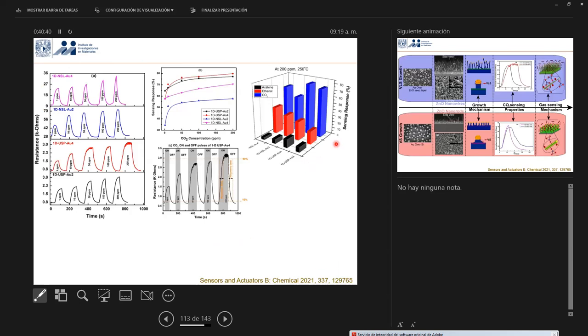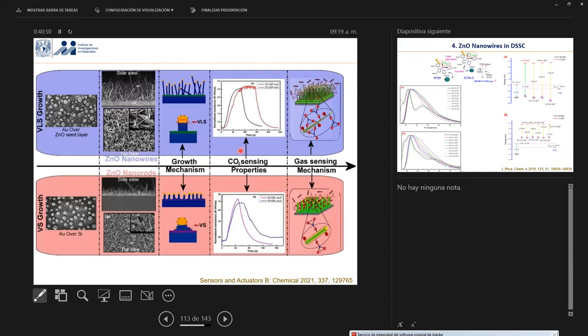And also we studied the selectivity of the gas. We did some studies with different kinds of acetones, alcohols, ethanol, CO2, and we found they were highly selective for CO2. And the main mechanism was, in the case of nanowires, they have a double interaction with the carbonate group from CO2. But in the case of nanorods, only one kind of interaction. So in nanowires, we have enhanced interaction. That's why the sensitivity is quite high as compared to nanorods. But as the interaction is only at one particular site in nanorods, they were quite faster.